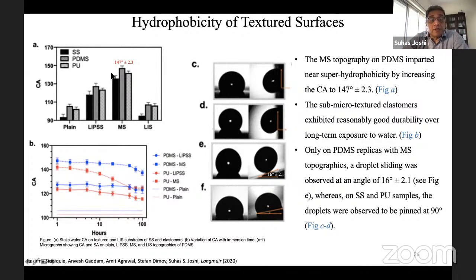So one of the contact angles, you can see that the contact angles on the multi-scale structures are much higher. You can see the multi-scale structures as they are, and then they are replicated on PDMS and PU. Then the replicated structures have much higher hydrophobicity. Also, these structures have a large durability over a long time.